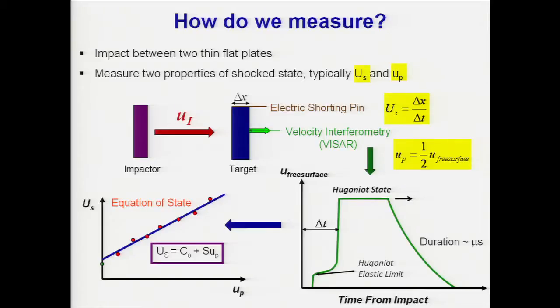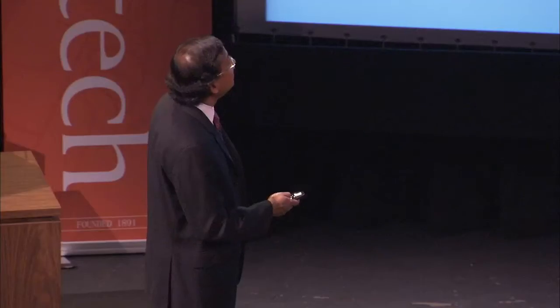We get the particle velocity as a function of the impactor velocity. This shockwave speed is a property of the material which we measure, and it turns out that for most materials we have a linear relationship between the shockwave speed and the particle velocity, or the imposed motion. And this is the so-called equation of state, which can be used for calculating our pressures.